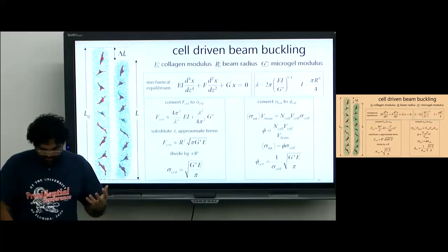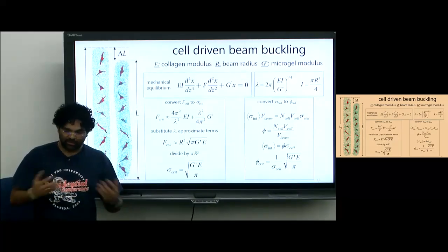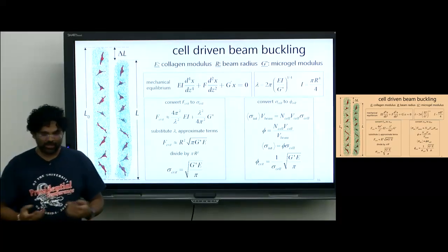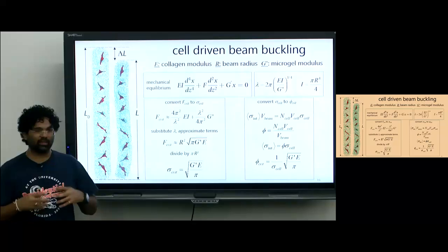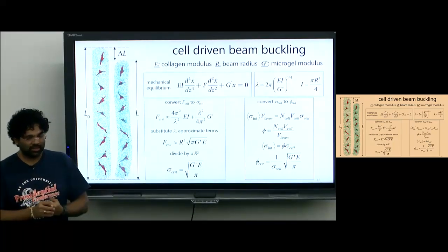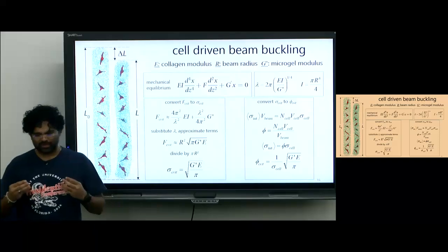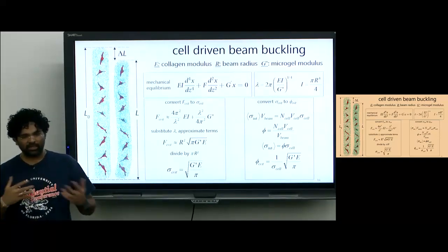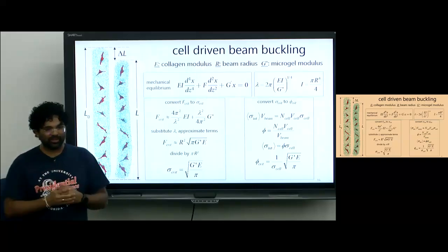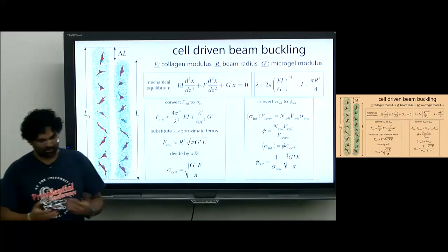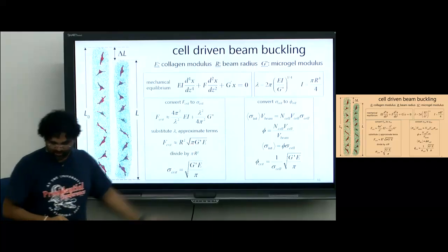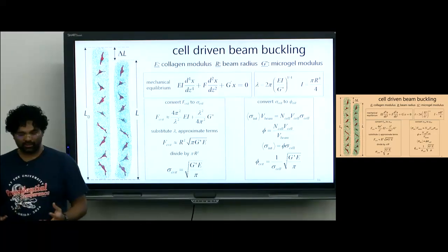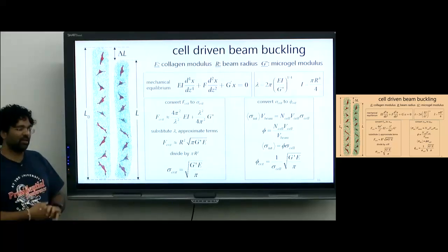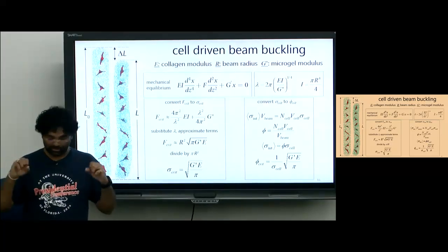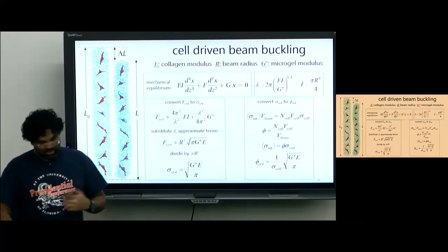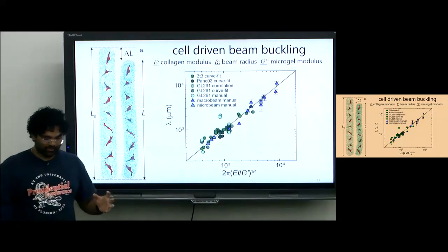Because there was beam buckling, they went on to characterize the beam mechanics. In this case, the difference is that it's a beam embedded in another material with an elastic modulus. You can think of it as the mechanics of steel beams embedded in concrete, except in this case the beams and the concrete are both soft. It's not as stiff as metals, right? But you can write down the fundamental equations and back out the critical stress that you need to buckle these beams, and also the critical diameters at which the beams would buckle or stay stable.